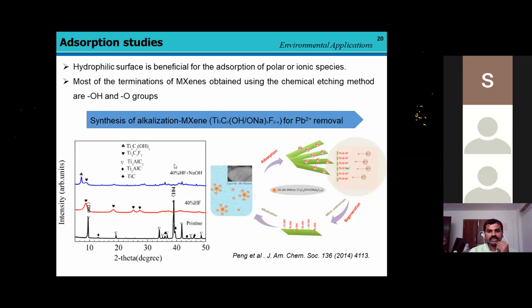You can see here there is a pristine form of MXene. Then the d-spacing of 002 has shifted towards a lower angle of 2 theta, which confirms that the structure has delaminated, which means that sodium ion has been incorporated between the layers. Sodium ion has been incorporated between the layers, so the sheets are exfoliated. Also, further,